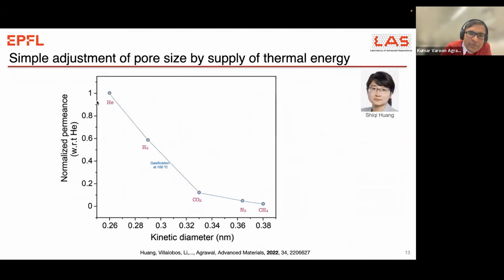And what we are doing is looking at which gases come across graphene. What we saw is helium coming up the fastest, followed by hydrogen, CO2, nitrogen, and methane. This is along the expected size of the gas molecule. Helium is the smallest, so it comes fastest, then hydrogen and CO2. So this is a true filtering effect where the smaller molecule is coming faster.